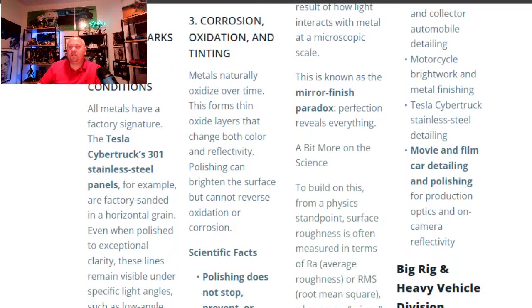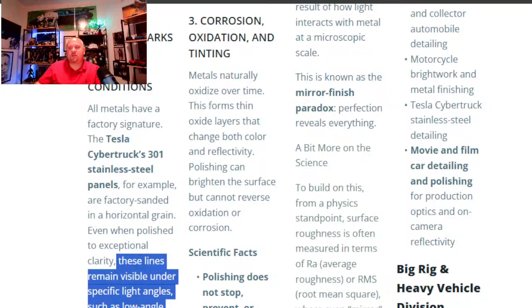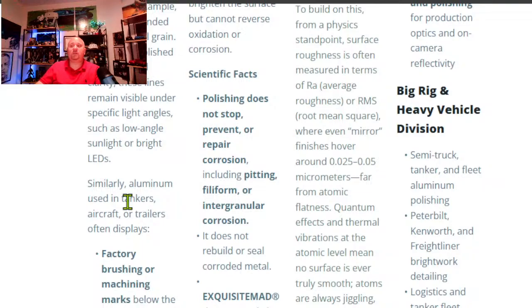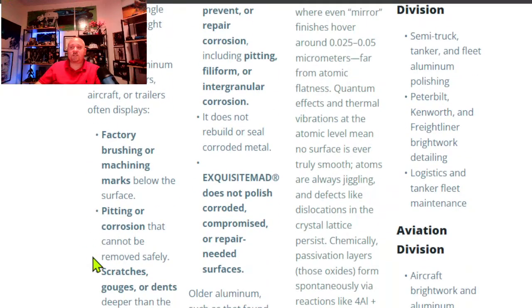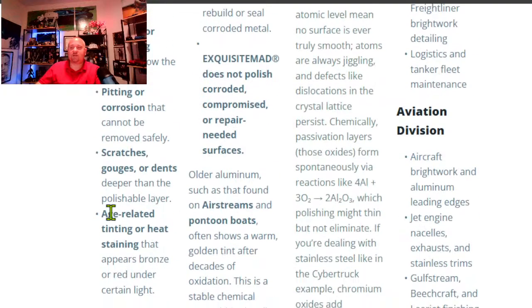For instance, if you're looking at Teslas, Teslas have pre-sanding marks in a horizontal grain. Even when polished with exceptional clarity, these lines remain visible under specific angles such as low-angle sunlight or bright LEDs. Similarly, aluminum used in tankers, aircraft, trailers, etc., often displays factory brushing or machining marks, pitting or corrosion below the surface that cannot be removed safely, scratches, gouges, or dents deeper than the polishable layer, and age-related tinting or heat staining that appears bronze or red under certain light.